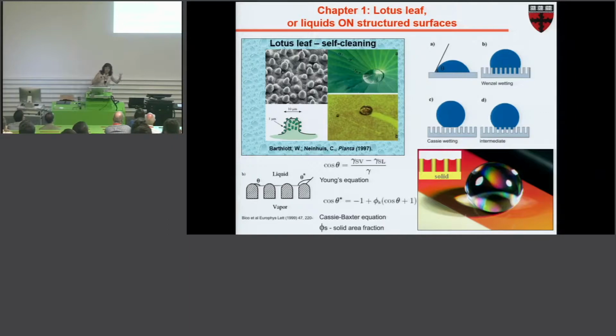On air, liquids would form a full sphere, which means the contact angle with air is 180 degrees. So if you have a liquid on a structured hydrophobic surface, for example, then its angle would be between what it makes on a flat surface, let's say 120, and 180. So in fact, the liquid sitting on this complex substrate is experiencing more air if you structure it in such a way that the solid fraction is very low, and the outcome of that is the droplets are nearly spherical.